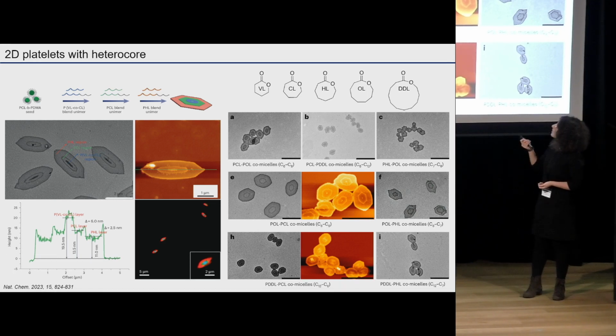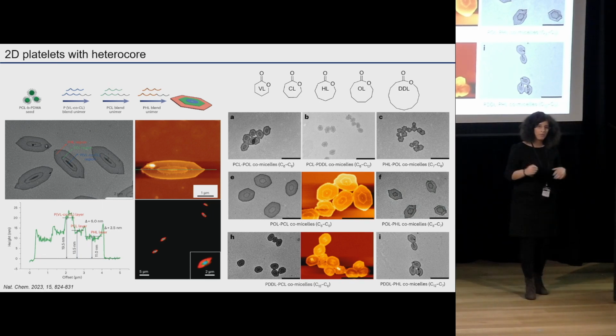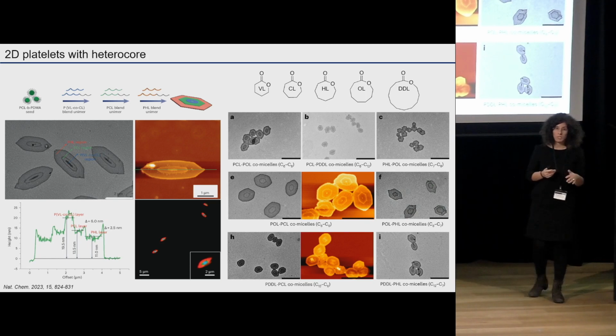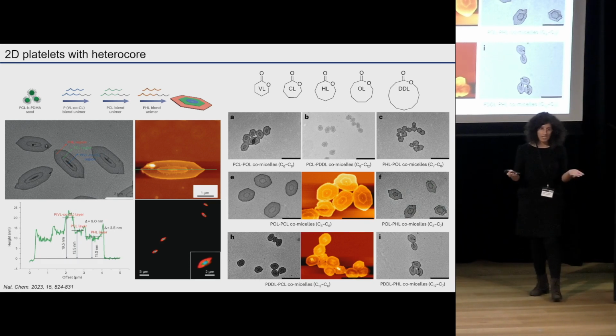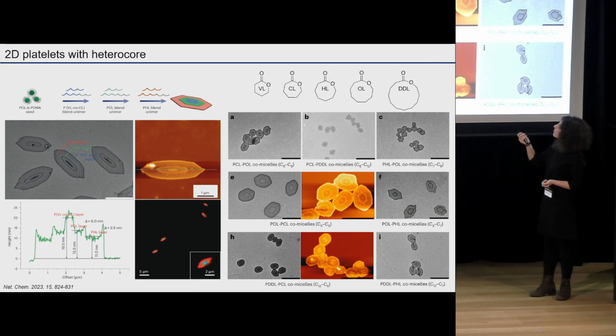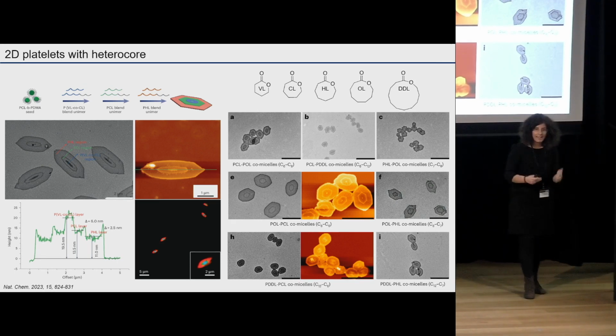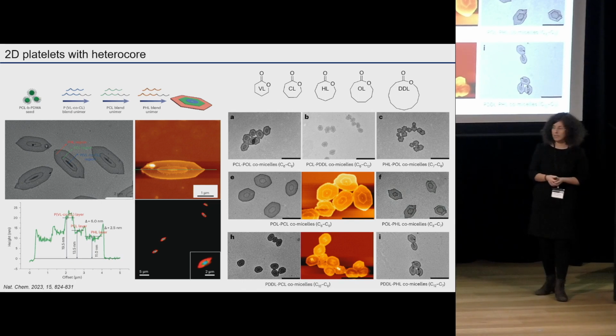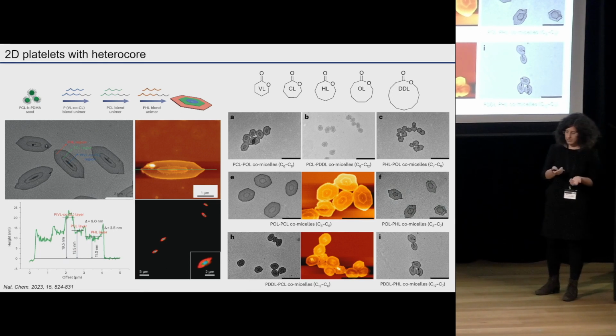And in this case, what we did was to simply change the size of the ring that we're dealing with. And by changing the size of the ring, we also wanted to see if that has an effect on the nanoparticle morphology, but also on degradation of the nanoparticle, because theoretically, if you go from a 6-member ring to a 12-member ring, you are delaying the degradation of your particles, so you can actually control that aspect as well. So as you can see here, we can build nanoparticles using any of these polymers.